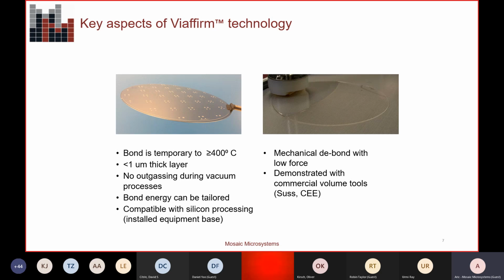But we've had a customer who wanted to put a very thick coating on the device wafer, use our handle to support it during debond, and that standard bond energy wasn't quite enough to maintain a good full bond. It didn't pop off, but it didn't maintain a good full bond. So we were able to dial in a bond energy that was 2 times the standard level, and it worked very well to enable a very thick coating to be processed on a 100 micron thick piece of glass in an 8-inch format. So that tailorability can be important depending on what you're trying to do with the thin glass and what your downstream processes are.